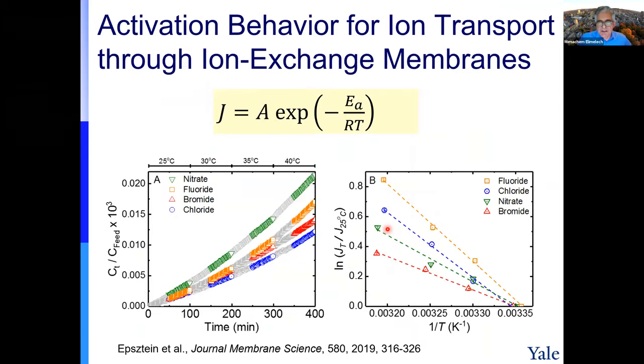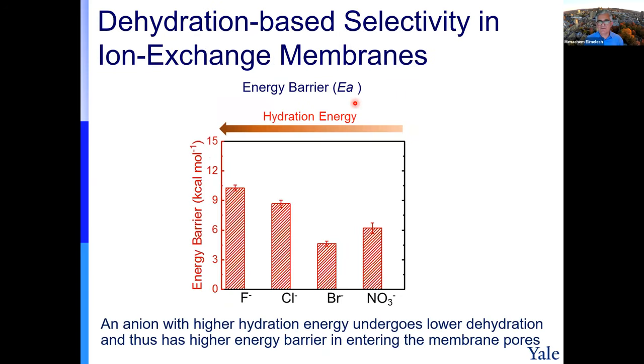And we said, let's apply it to an ion exchange membrane. So this is an ion exchange membrane. We can measure different salts: sodium nitrate, sodium fluoride, sodium bromide, sodium chloride. We can measure the flux through the membrane at different temperatures. We can apply the Arrhenius type equation that you know from chemistry. Based on the slope of the flux versus one over the temperature, as you know from basic chemistry, we can calculate the energy barrier. And I would like to show you some data.